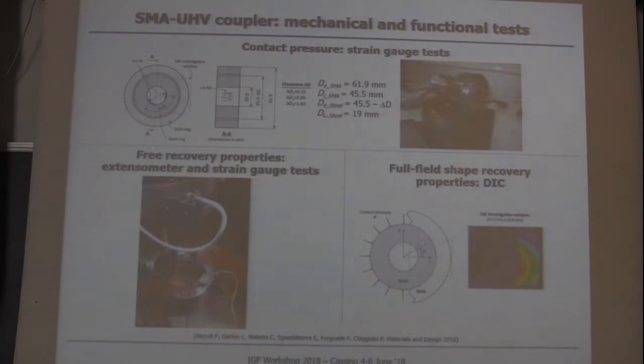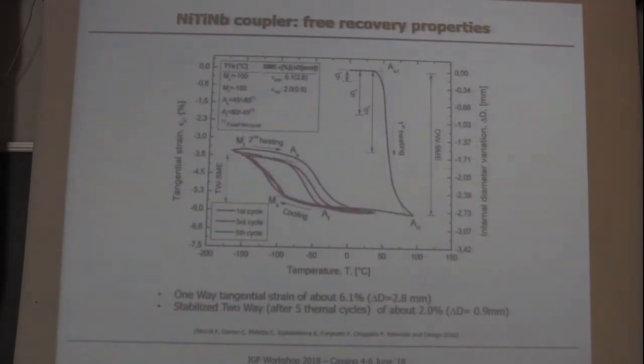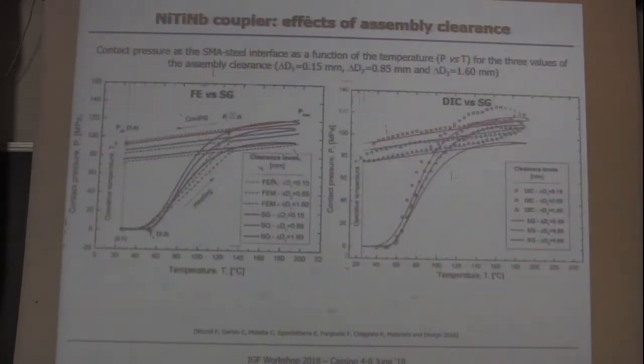After training, the ring is smart — it has the ability to contract upon heating and cooling. We did measurements to measure both the so-called free recovery capabilities, which is the possibility of the ring to change shape when it is unconstrained, and also the so-called stress recovery capabilities — meaning activation against a steel pipe, which is a condition very close to the real application.